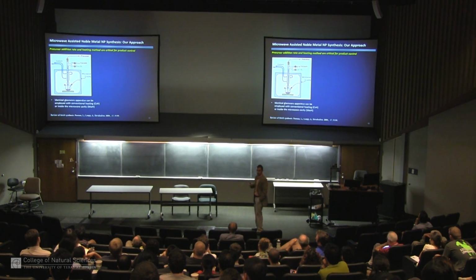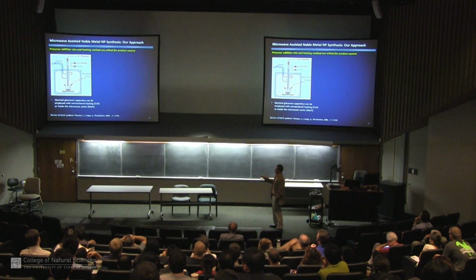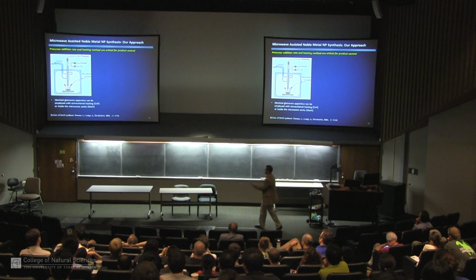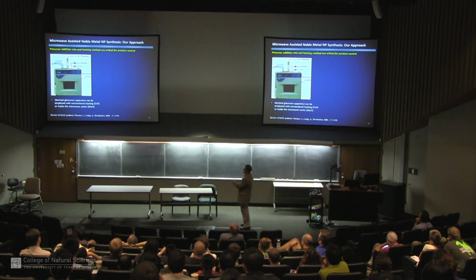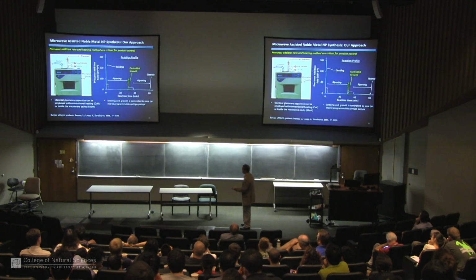Now this is our main contribution to this field in the past few years, the use of microwave synthesis to change this chemistry. And so we adapted a microwave reactor in which we used regular glassware so that we could directly and carefully compare the effects of microwave heating versus conventional heating and nothing else different. So we would physically take the glassware out, use it in all of that, do the same reaction in the microwave cavity. This is one of these scale-up acid digestion microwaves, and the good thing about microwave chemistry is if it works on a small scale, you can scale it up to flow chemistry, and it works on a larger scale.